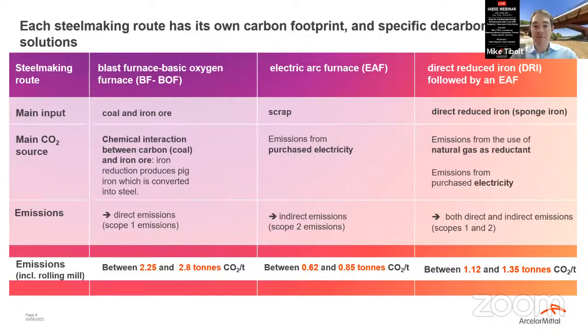Then we have the electric arc furnace, where we use scrap to produce the steel. The main CO2 source in this case is the purchased electricity that we need to heat up the electric arc furnace. So these are indirect emissions, because we do not directly produce the electricity that we use in our plant, but we purchase it. And those emissions are, of course, lower. They lie between 0.62 and 0.85 tons of CO2 per ton of steel produced.